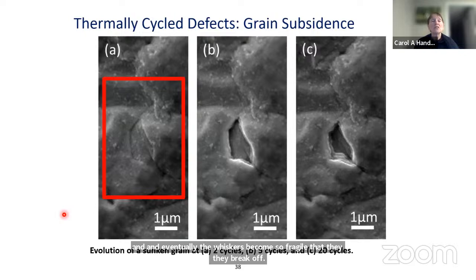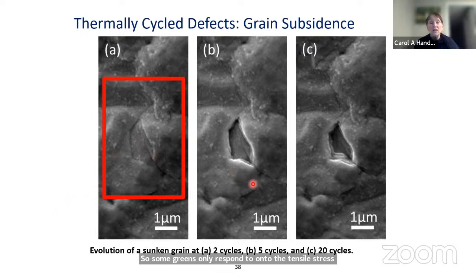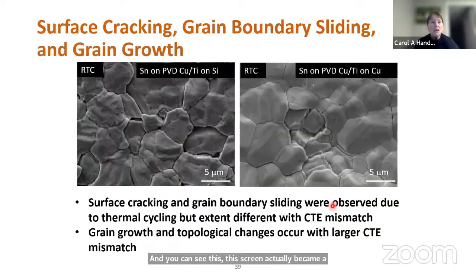And here's a case where there's a sunken grain. So some grains only respond to the tensile stress component of it. And so this is at 2 cycles, 5 cycles, and 20 cycles. And you can see this grain actually became a source of atoms for stress relaxation in other places in the film. So we've done a lot of work on trying to classify what the different phenomena were.